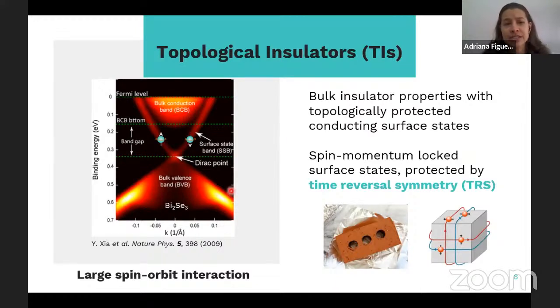But what you see on the band structure of a topological insulator is exactly that you have a bulk band gap that coexists with those surface states that are metallic-like. And those surface states are characterized by spin-momentum locking that is protected by time reversal symmetry. All these characteristics of the TI are a consequence of the large spin-orbit interaction. And that's why these materials are very attractive for applications in spintronics and spin orbitronics.